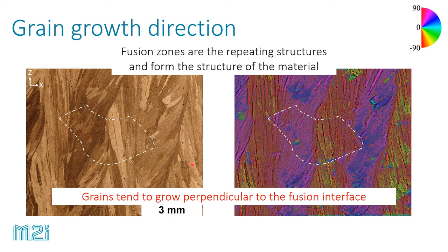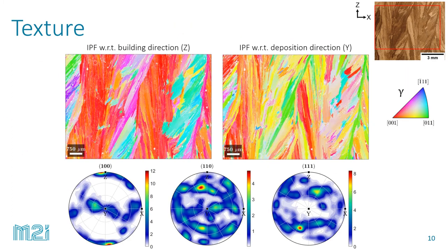The next question is whether we also see the same trend in terms of texture. We performed electron backscatter diffraction analysis to study the microtexture of the part. By doing this, we identified a dominant ⟨100⟩ direction in the overlapping regions. Similar to what we saw before, we still have this periodic repeating in both overlapping regions, which means that these regions actually promote epitaxial growth, and consequently they would affect the mechanical properties depending on how you load this component.